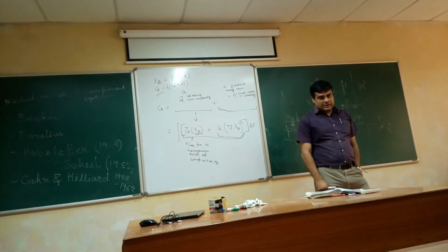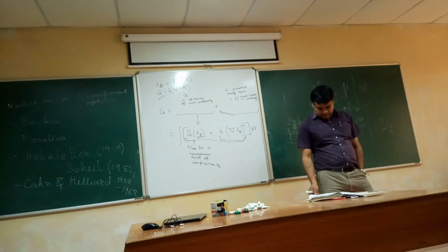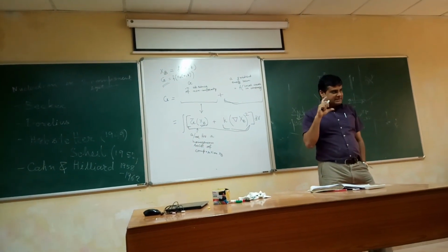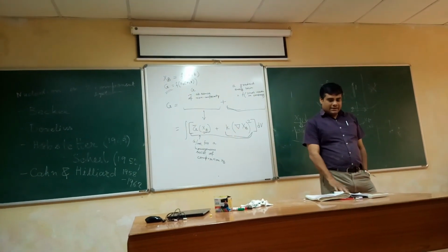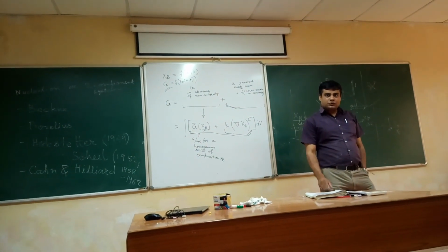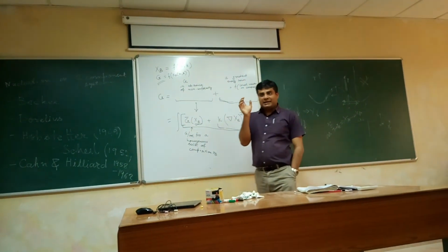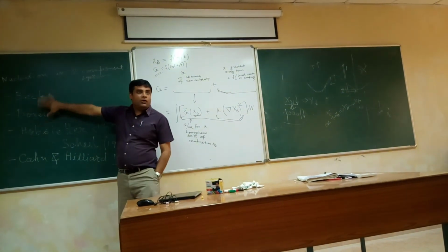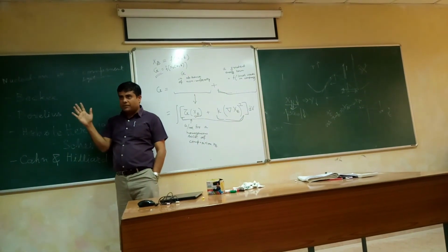And as the supersaturation becomes large, then the delta G star comes down, and at spinodal point, if your matrix composition becomes close to your spinodal point, then the interface width... For Becker, Borelius, Hobstetter, all three of them, interface is a very sharp interface. There is no width of interface.